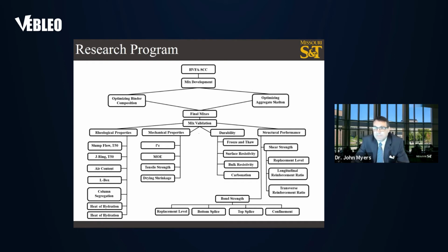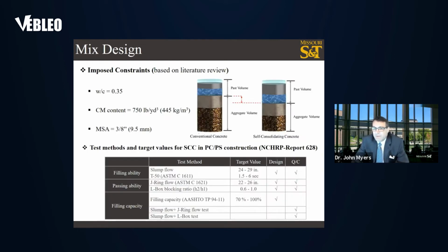in the various categories. Based on literature and practical considerations to design mixtures with SCC rheology, the following constraints were imposed. As seen in this figure, SCC needs to have a paste volume more than conventional concrete mixes to enhance the concrete flowability. The target rheology properties were selected based on the intended application of SCC recommended by NCHRP Report 628, which is presented in this table. So here you can see the target values for design, for quality control, and the various tests that are used to evaluate it, as well as the targeted water cement ratio, the CM content, and the maximum aggregate size.